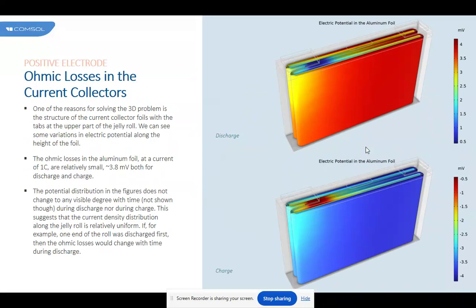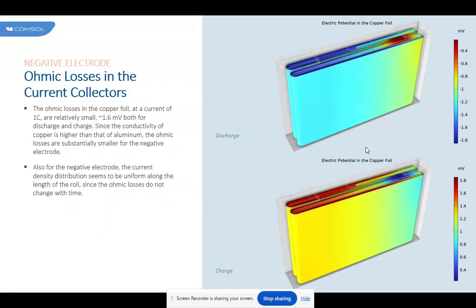If, for example, one end of the roll was discharged first, then the ohmic losses would change with time during discharge. Negative electrode ohmic loss in the current collector. The ohmic losses in the copper foil at a current of 1C are relatively small, about 1.6 millivolts, both for discharge and charge. Since the conductivity of copper is higher than that of aluminum, the ohmic losses are substantially smaller for the negative electrode. Also, for the negative electrode, the current density distribution seems to be uniform along the length of the roll, since the ohmic losses don't change with time.